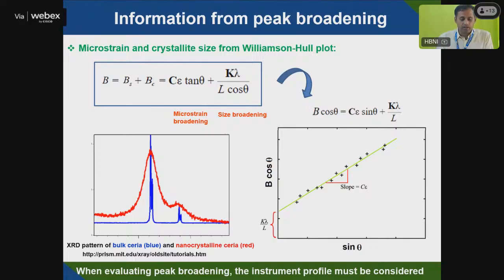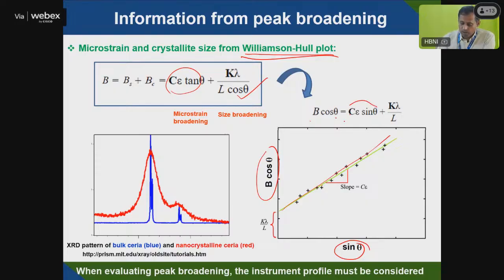So another method of calculating strain and crystallite size is the Williamson-Hall plot. Here you have to plot beta cos theta versus sin theta, and then fit a straight line to the data, from the slope and intercept. The equation is C epsilon tan theta plus K lambda by L cos theta. So that will be rearranged: beta cos theta equals C epsilon sin theta plus K lambda by L. From the slope you will get the strain, and from the intercept you will get the particle size.